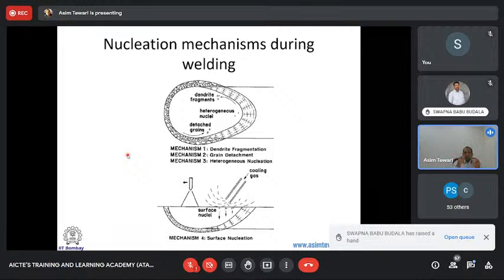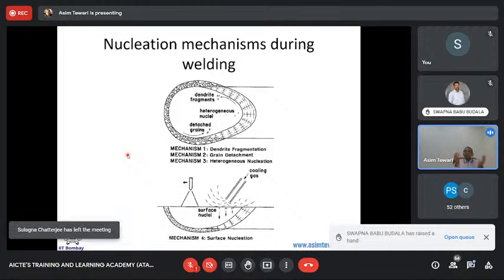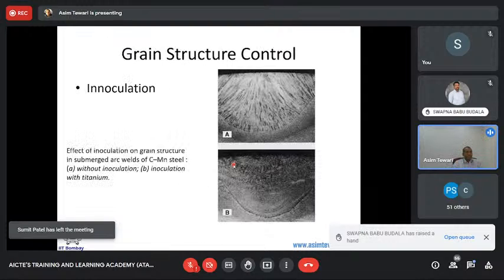We look at how the fluid is flowing in the melt pool, and how the heat transfer is happening in one weld pool. And this leads to three different mechanisms. There's a dendrite fragmentation mechanism, a grain detachment mechanism, and the mechanism of heterogeneous nucleation. All of them put together would lead to different structures.